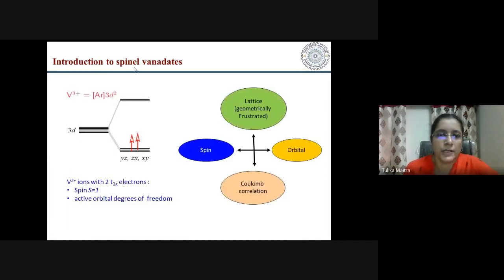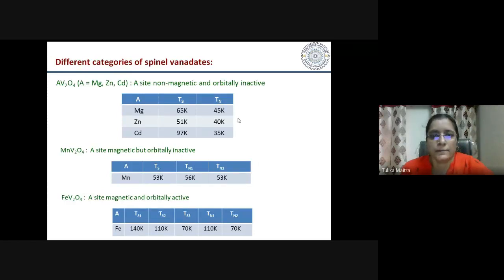In our case, in spinel vanadate, we have vanadium as the B site ion, which is in the 3+ state. So we have two d electrons here, which are in a high spin state because of large Hund's coupling. So the spin degree of freedom is active, and because there are 3 orbitals and 2 electrons, the orbital degree of freedom is also active here. It's not frozen. So in these compounds, there is a very interesting interplay between the spin degree of freedom, the orbital degree of freedom, and the lattice, which is geometrically frustrated. And because these are transition metal compounds, the Coulomb correlation is also very strong. So there is a strong interplay between all these degrees of freedom, giving rise to very interesting transitions. There are multiple magnetic and structural transitions seen in these compounds.